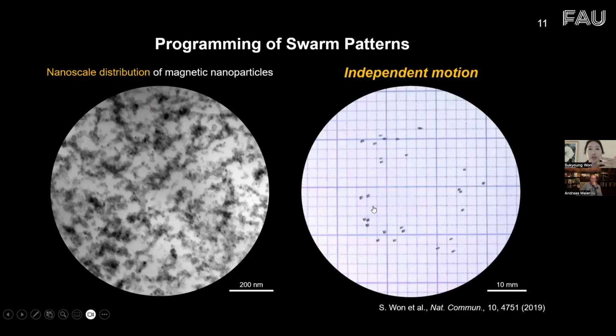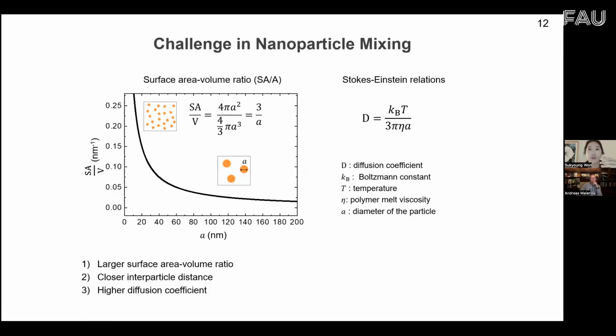So the first approach is that the magnetic nanoparticles are uniformly distributed on the nanoscale in the polymer composites to achieve independent motion of the multiple magnetic robots. This can minimize interruption from the magnetic force between the microrobots. However, the nanoparticle dispersion is challenging due to their high surface area to volume ratio and their closer interparticle spacing compared to microparticles at a given concentration.